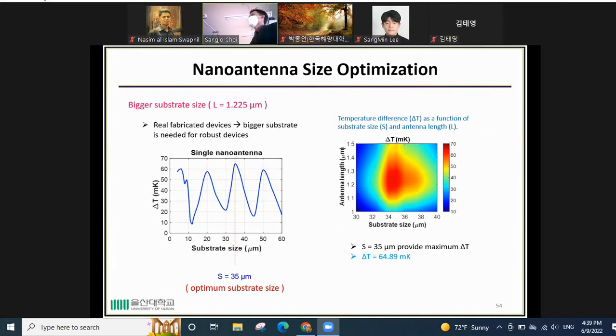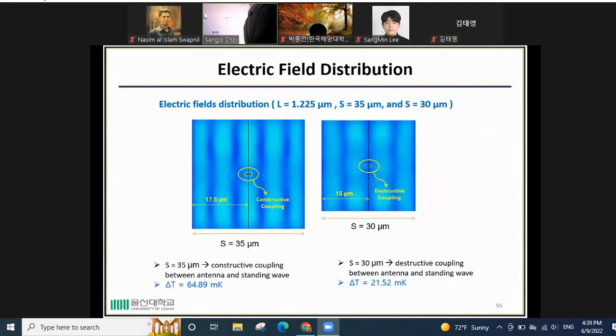You can see also this is the contour plot of the substrate size as a function of the antenna length. Substrate size of 35 micrometer provides 64.89 millikelvin temperature difference. We also analyze the electric field distribution to see the coupling mechanism between the antenna and substrates. This is the substrate size of 35 and we compare with the 30 substrate size. In the 35 case, we see constructive coupling between antenna and standing wave, so that delta T becomes higher, 64.89 millikelvin. Compared to this, you can see destructive coupling between antenna and standing wave, which generates delta T of 21 millikelvin.